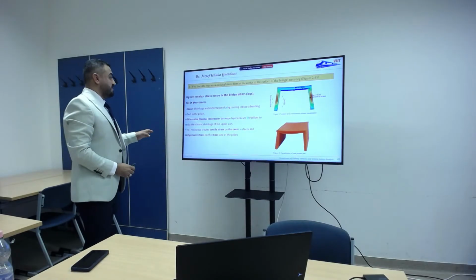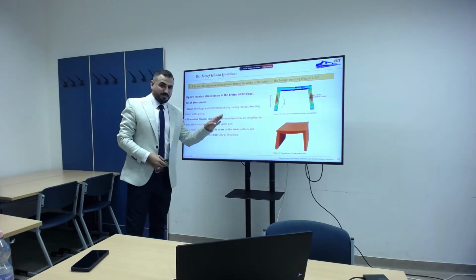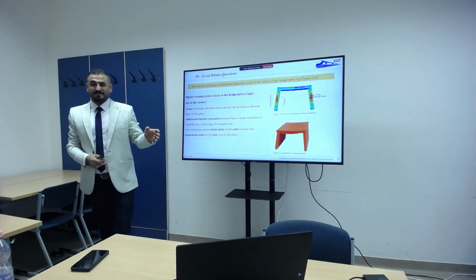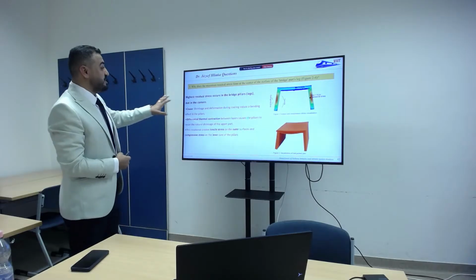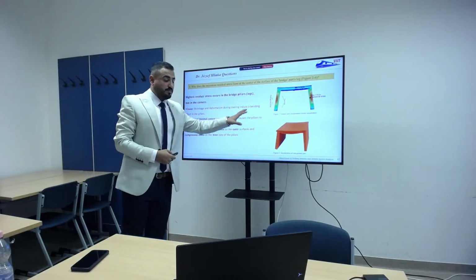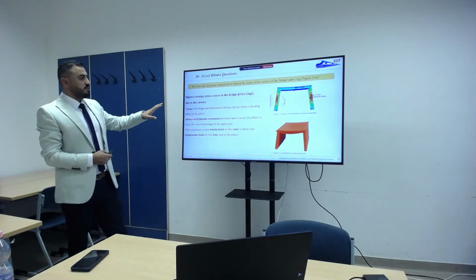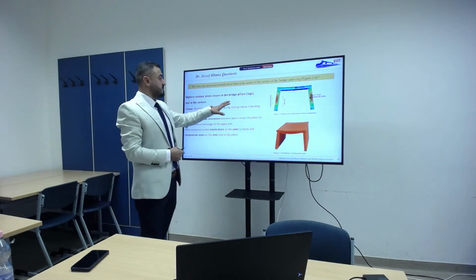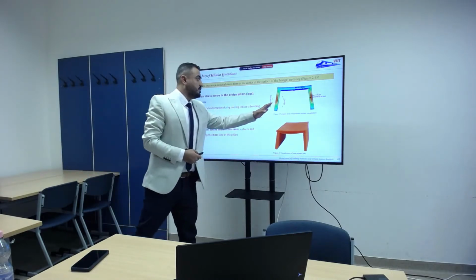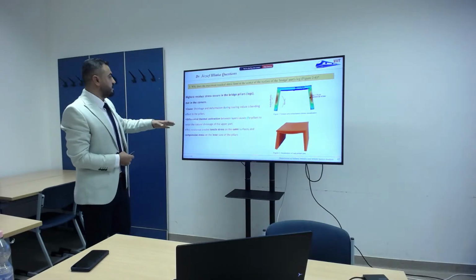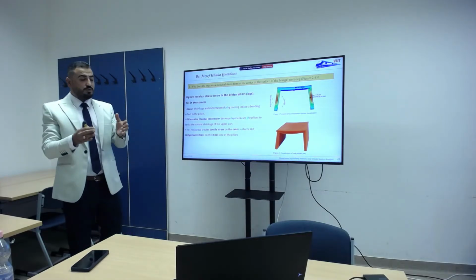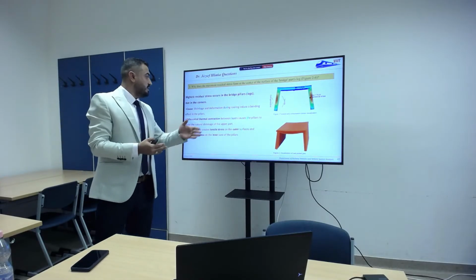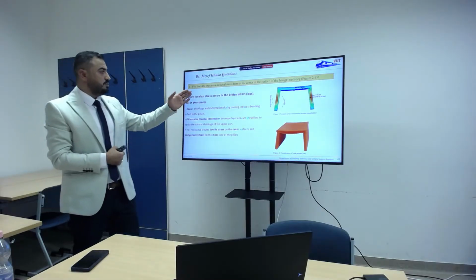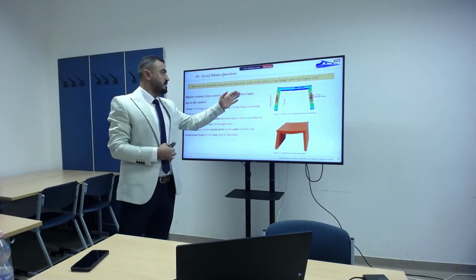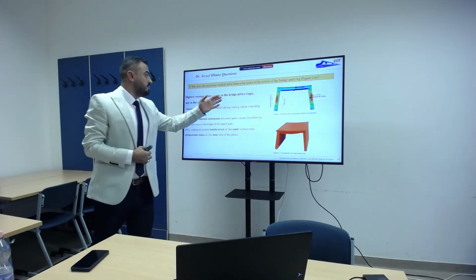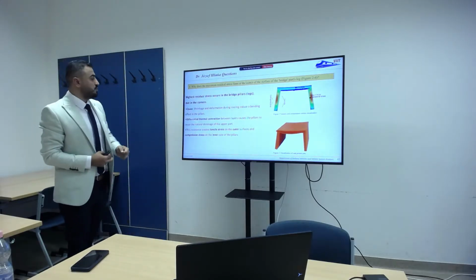Regarding the first question, I was expecting this question from the journal review, but it came from you. As you can see here, I used this bridge geometry, and the maximum residual stress, as you mentioned, was in the pillar, in the leg. The clarification for that: the shrinkage and deformation during cooling induced the bending effect. So it happens because of the bending effect induced by the shrinkage and deformation during cooling.